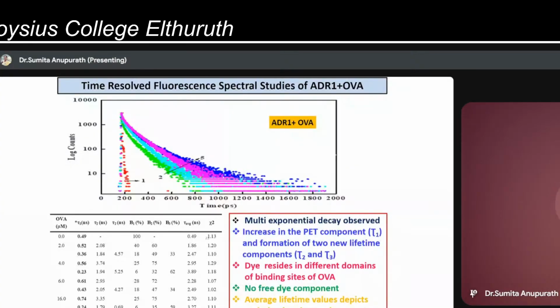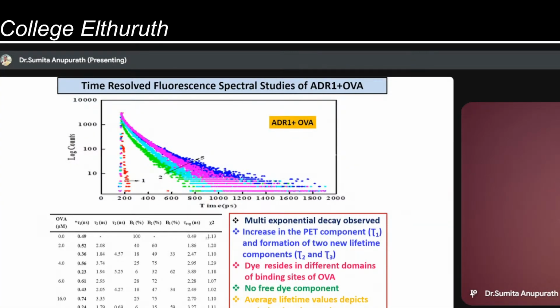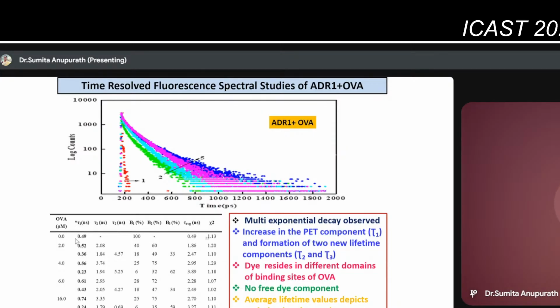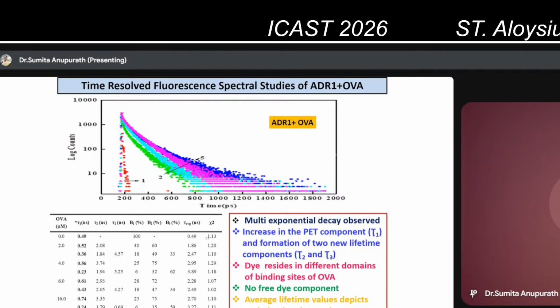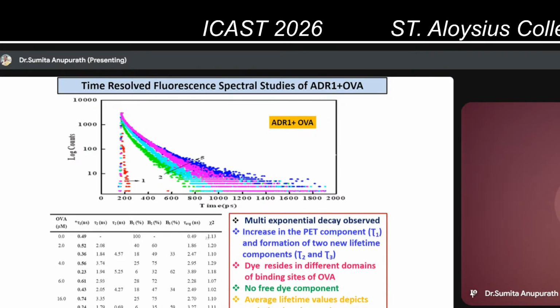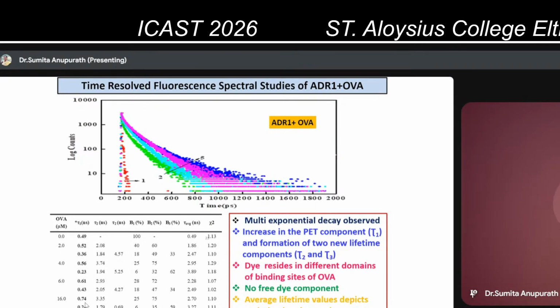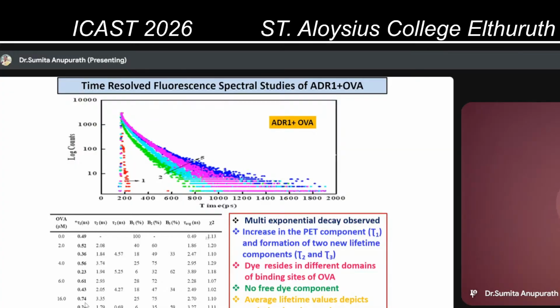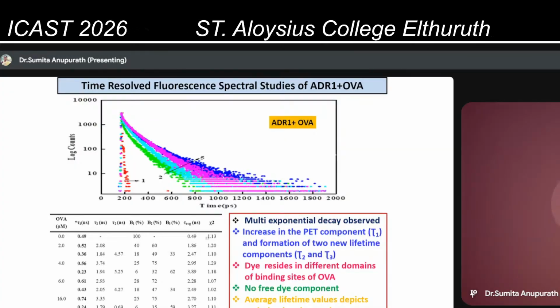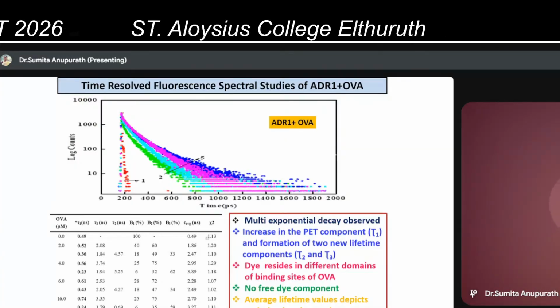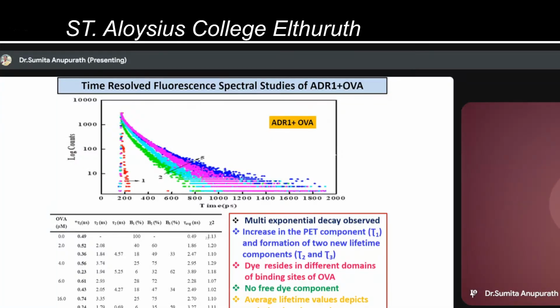Now that was understood by the increase in the PET component. If the dye was free, the lifetime would have been 500 picoseconds or 490 picoseconds, but it gradually increased to 740 picoseconds. So that shows that the dye was completely trapped inside the ovalbumin, or we can say the dye was completely interacting with the ovalbumin.